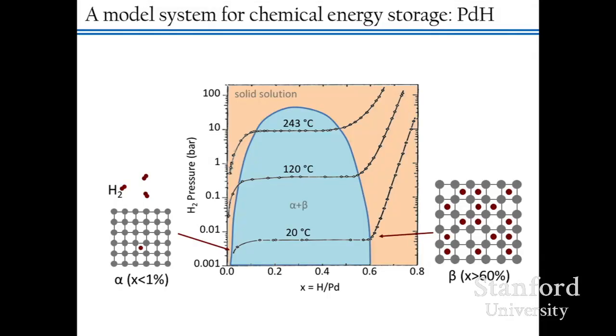So instead of looking at lithium intercalation into nanoparticles, we're going to look at a much simpler system, but one that has very analogous physics. It turns out the thermodynamics of the system are quite similar to the thermodynamics of what is thought to happen in lithium ion systems. So it's a system of palladium hydrogenation, and it's a very old system. Basically, studies of the system started back in the mid-1800s. It was one of the first phase transformations in bulk to be well understood. And in bulk, here's the phase diagram.